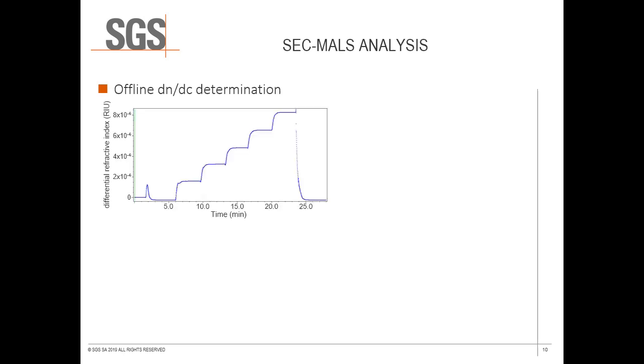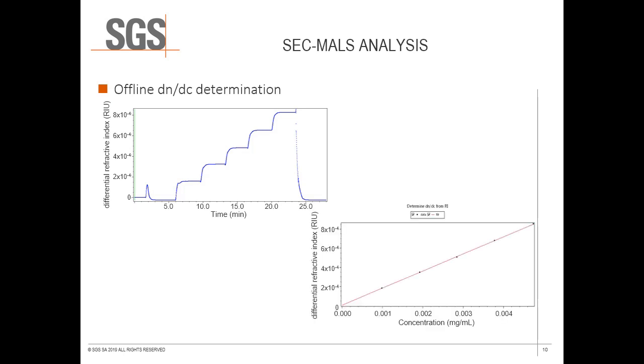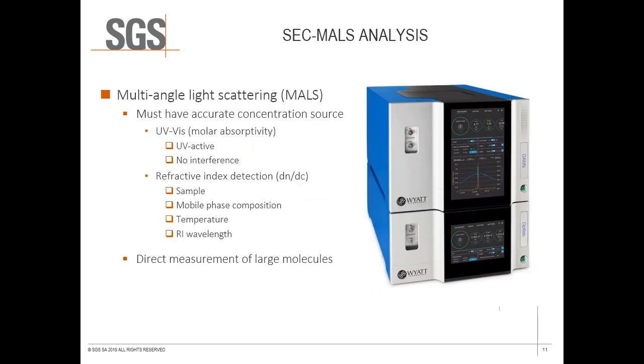Alternatively, if complete dissolutions of pure dry sample can be prepared at various concentrations, they can be infused directly into the flow cell of the refractive index detector, and the refractive index measured relative to pure solvent. This differential refractive index is then plotted versus analyte concentration, and the slope of a line fitted along these points is the dn/dc. dn/dc measurement can be particularly challenging when the sample is impure or contains an unknown amount of insoluble material. Despite these challenges, SEC-MALS analysis remains the preferred method for characterizing the molar mass of large molecules.